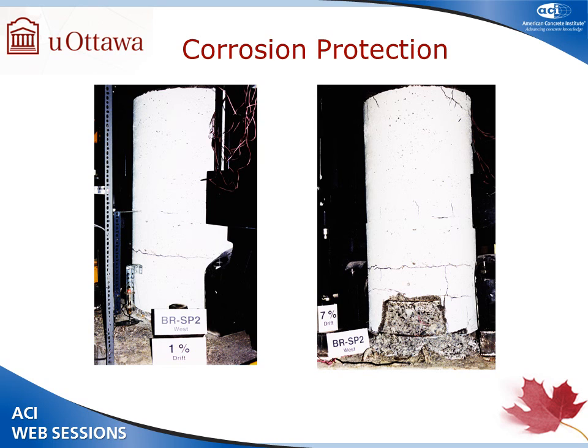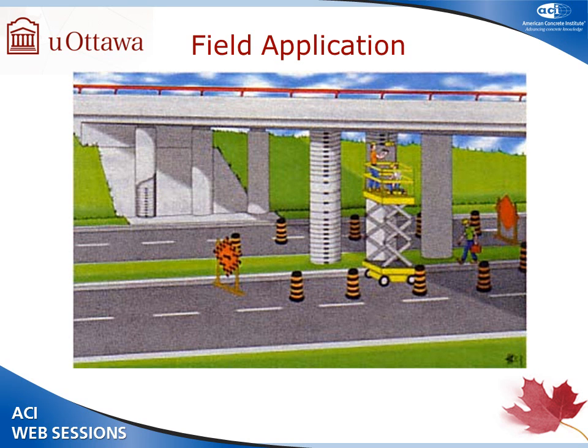And this is the corrosion protection shotcreting. We used different types, with and without bonding agent, without fibers, but they all behaved roughly the same. On the right-hand side, you see the shotcrete finally falling off as late as 7% drift. So the performance was fairly good. In terms of field application, it only requires a two-person crew, and we are able to do this in half a day in a field environment.